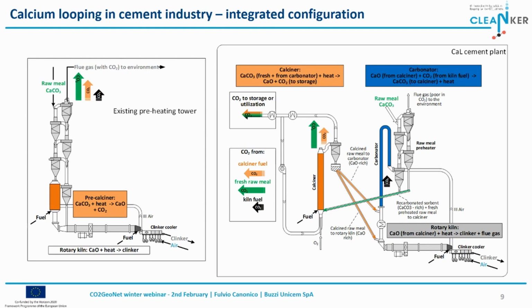So you have the existing preheating tower in a cement plant. You can see here the kiln and the preheater tower. Basically, we are using raw meal, calcium carbonate, that together with clay will react in the kiln in order to form the clinker. So basically a combination of calcium silicate.